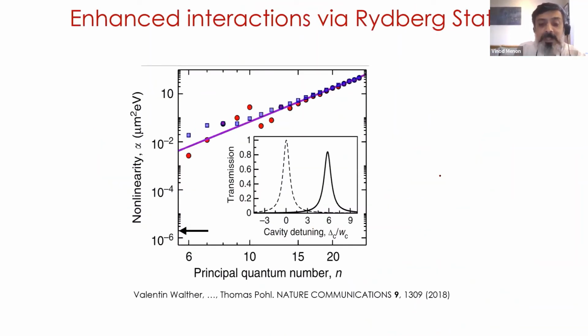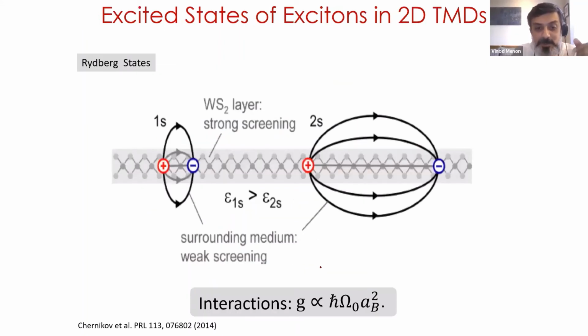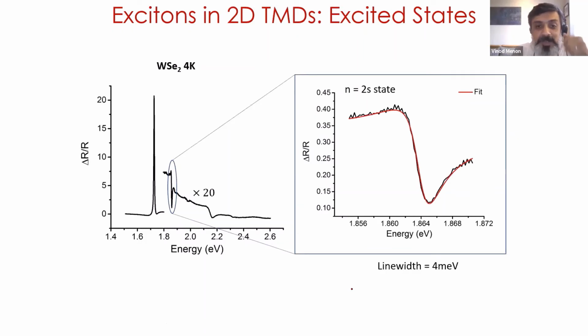So this is where the Rydberg states come into the picture. Theoretically, it has been shown that if I go to these larger n Rydberg states, then I will get increased nonlinearity. So we wanted to explore this property. We went back to the 2D materials, and it turns out the interaction strength is proportional to the square of the Bohr radius. So we wanted to ask whether this is indeed the case. We went ahead and made a system, and the question we were asking was, does the interaction strength of the 2s exciton, for example, scale with the Bohr radius?